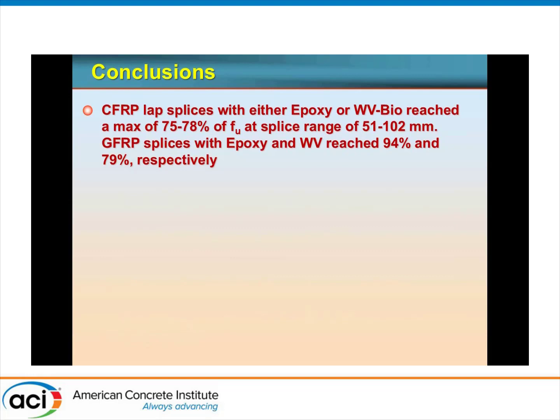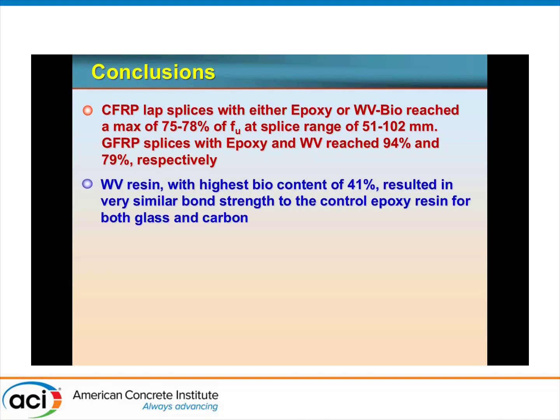The lap splices, with either epoxy or WV, because that's the only resin we tested for lap splices, reached a maximum anywhere between 75 to 78% of the full tensile capacity within the range of 2 to 4 inches overlap. For GFRP, we reached more, up to 94% or 79% for the two resins, respectively.